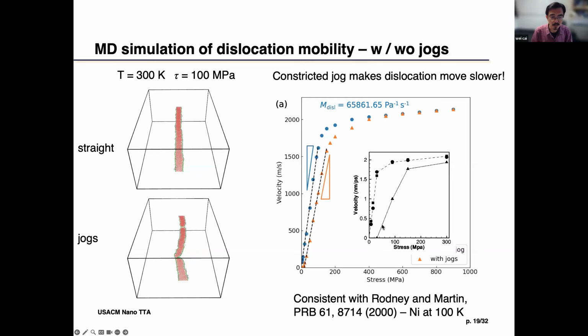But other than that work, in all the dislocation mobility studies in this multi-scale hierarchy, most of the simulations never considered jogs. And there's nothing wrong with that mobility, but the comparison with experiment is teaching us that we have to consider jogs. If not, then the mobility we're using is the mobility of straight dislocations, and the dislocation that's moving during plastic deformation is not moving at that mobility.